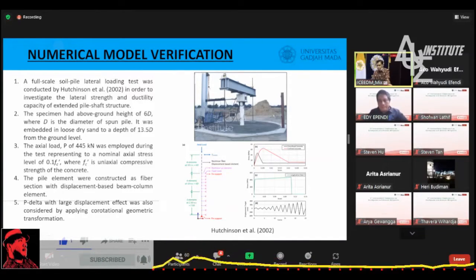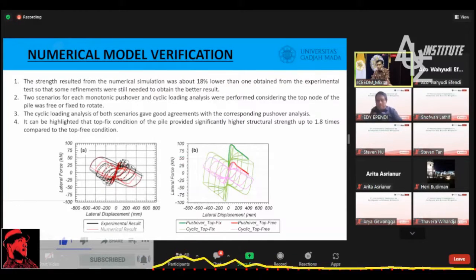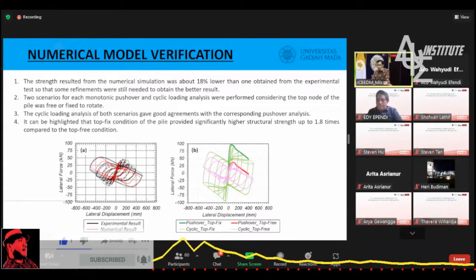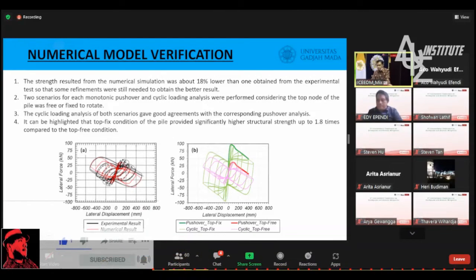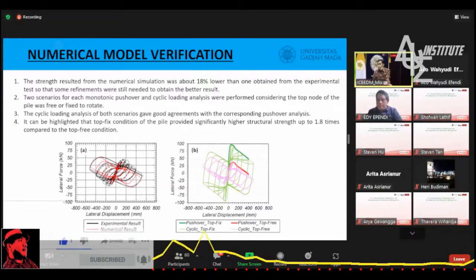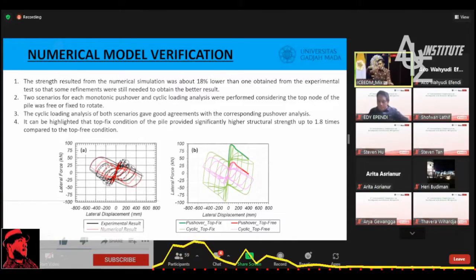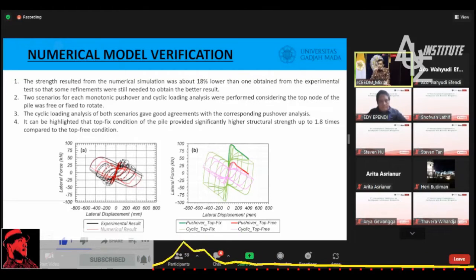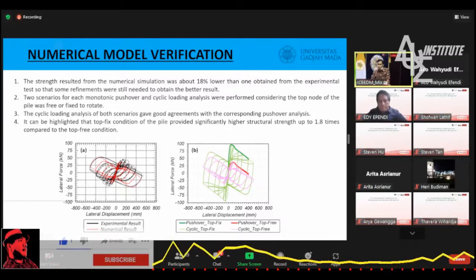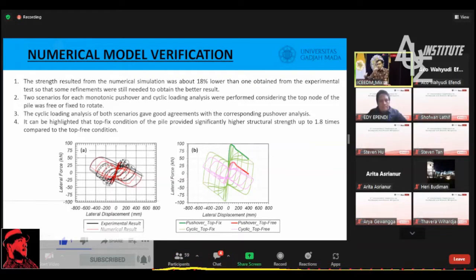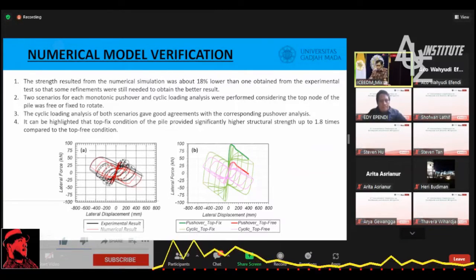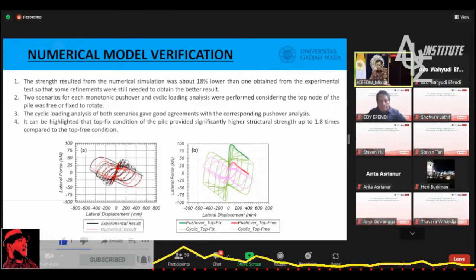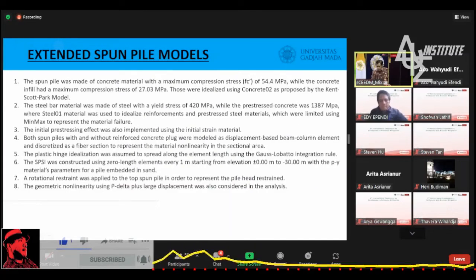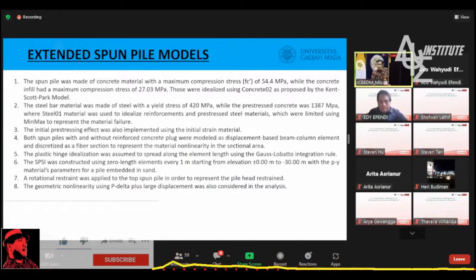And then here are the results. In graph A, the experimental result is the black line, and the numerical result is the red line. They have a good agreement. Here the numerical model is the freestanding pile without restrained moment, because it is freestanding. If we implement it in the slab-on pile, the top of the pile will have a restraint moment. So we try to give the restraint moment at the top of the pile. The result is a slope in the green color, so it has larger lateral strength, of course.